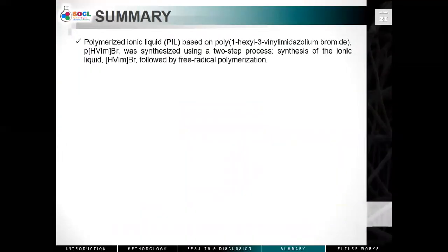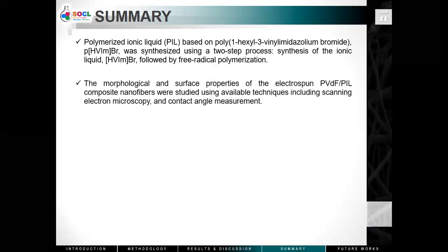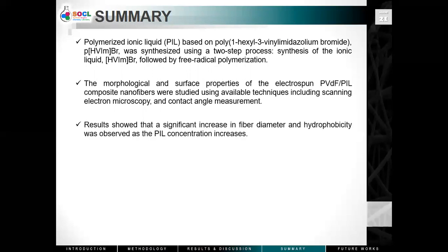To summarize, polymerized ionic liquid based on poly-1-hexyl-3-vinyl-imidazolium bromide was synthesized using a two-step process. The morphological and surface properties of the electrospun composite nanofibers were studied. Results showed that a significant increase in fiber diameter and hydrophobicity was observed as the PIL concentration increases.